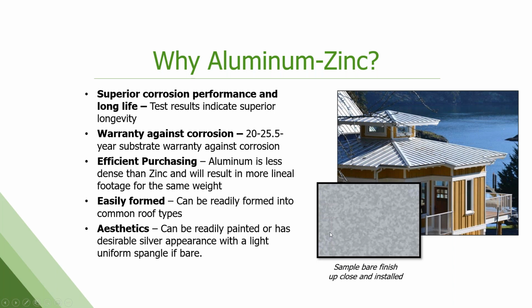So again, why this product? It's its long performance and its corrosion performance. It is warranted by most suppliers for corrosion, usually in the 20 to 25.5 year range, depending on the producer. It's efficient in purchasing too, because that aluminum density is so much less than straight zinc. You get more linear footage by weight out of this product than you do with galvanized. Form's great, can be used in all kinds of different shapes, sizes, and profiles, and has a really great aesthetic, especially bare. This is a bare roof here in this picture that hasn't been painted. Galvalume tends to have a very small, uniform spangle surface with a nice silver finish to it, but it's also a great surface to paint.